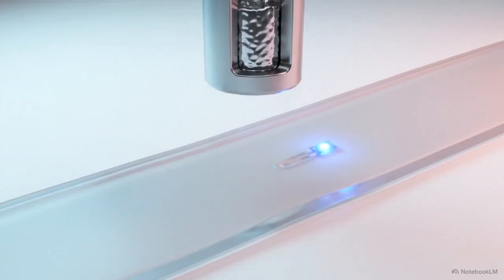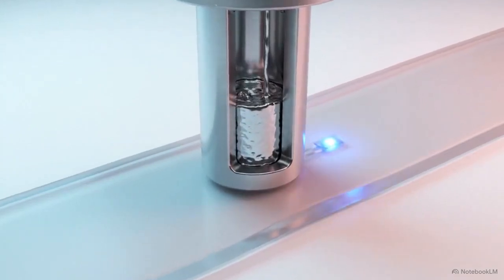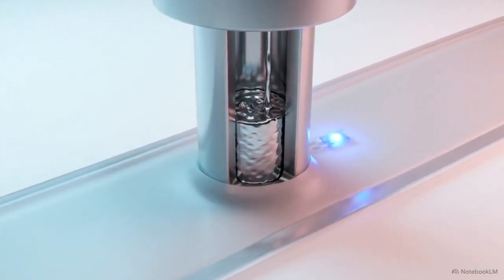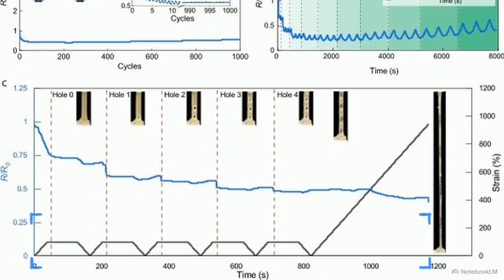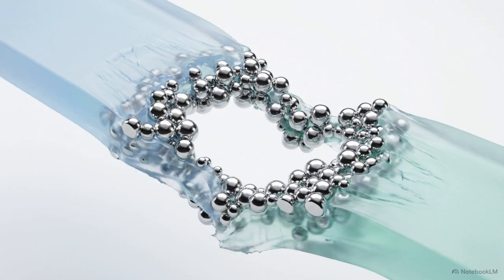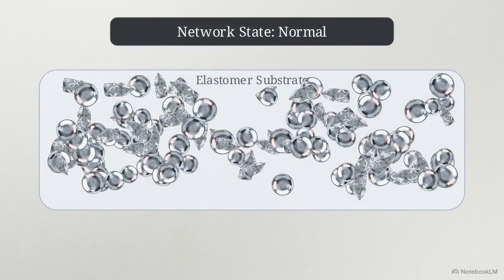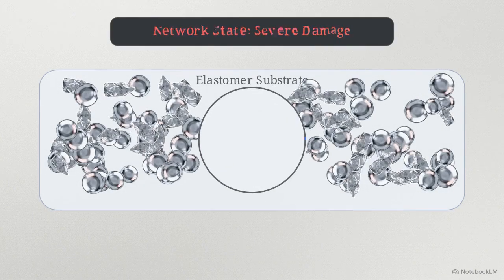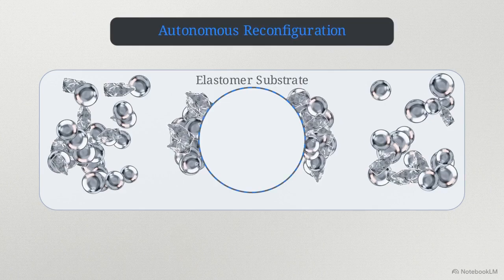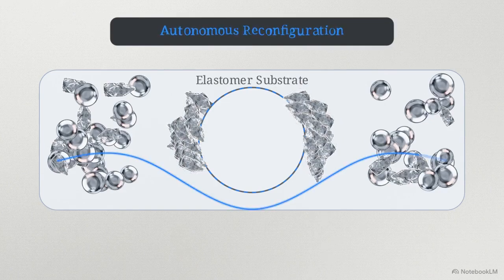To evaluate dynamic self-healing, the composite was subjected to a rigorous hole-punch stress test under active mechanical load. This chart shows the applied strain profile over time, paired with photographs showing the physical state of the dog bone sample, as 4 consecutive holes are punched directly through the conductive trace. Despite the physical removal of significant portions of the material along the functional line, electrical conductivity is seamlessly sustained. The measured resistance actually drops slightly after each severe damage event. The liquid metal network instantaneously reconfigures, forming new particle-to-particle connections around the rupture site.